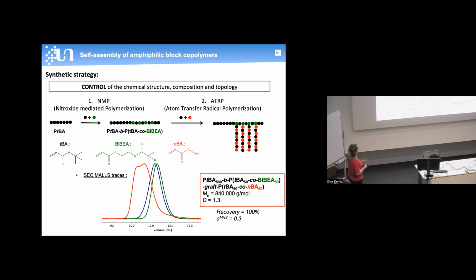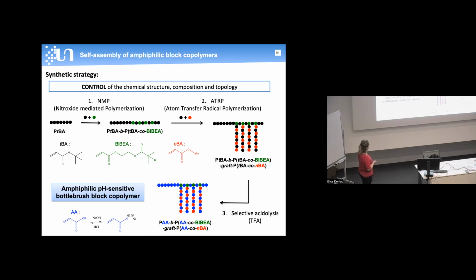So as you see, we could synthesize well-defined bottlebrush copolymers with a narrow molecular weight distribution and exhibiting a Mark-Houwink-Sakurada parameter alpha which is in accordance with a branched structure. And the amphiphilic block copolymer is obtained after a selective acidolysis of the tert-butyl acrylate units in black into acrylic acid units in blue.